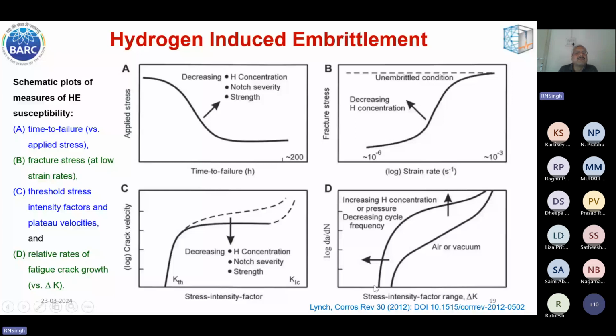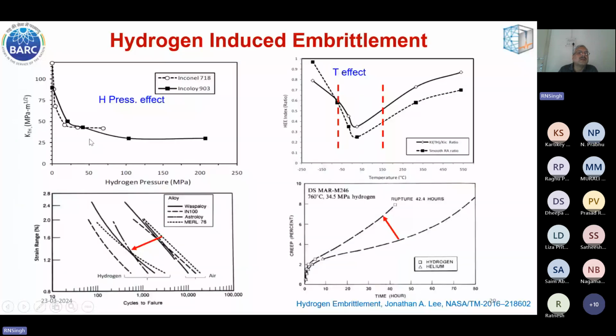So here, the hydrogen pressure effect is shown. The threshold stress intensity factor as a function of hydrogen pressure is shown. As the hydrogen pressure increases, the threshold stress intensity factor reduces. Here the temperature effect is shown. At low temperature, the hydrogen embrittlement effect is not there. At higher temperature also it is not there. It is the intermediate temperature regime where the hydrogen embrittlement effect is observed.